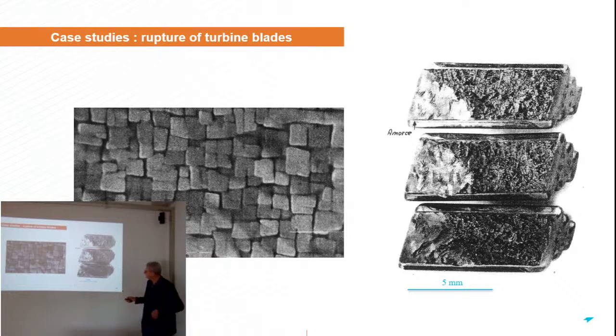Again, here a very nice micrograph showing the typical gamma prime microstructure of the nickel-based superalloy. No problem with the material here. And here you can see again the two-domain fracture surface, very typical of a fatigue fracture surface, with an initiation here and a propagation through this zone, and then the final fracture here. You can see about the same thing here and about the same thing here. So fatigue again here.